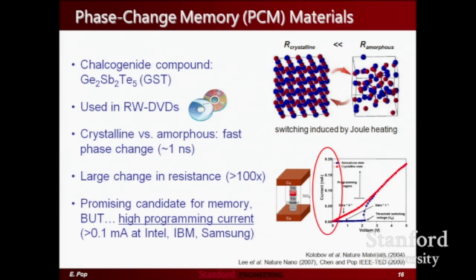It's a funny material. It's germanium, antimony, and tellurium. It's actually used in rewritable DVDs. This material or materials like it are used in rewritable DVDs. So if you own rewritable DVDs, you actually have this stuff already, even if you have Blu-rays and so on. On the back of a DVD, of course, the memory is written optically. It's written with a laser beam, and the laser beam basically just changes the refractive index of the material by essentially either crystallizing it or amorphizing it, depending on how much heat you put in with the laser. So that's kind of how it works optically.